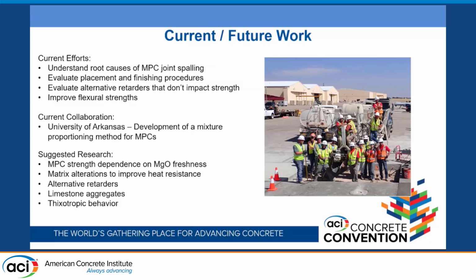So back on my time of set plot, just visually, I thought that if you keep it agitated, it won't set up for a while. And so I put it in a mixer and let it sit in a mixer for an hour, and it actually stayed fluid. But as soon as I took it out of the mixer, it flash set. So that's interesting behavior to me.